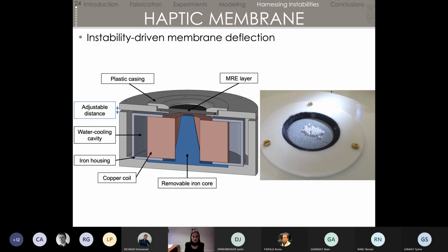So here you have at the top of the device an MRE layer inside a plastic casing, and then it's deposited on top of a coil with an iron core. And as you switch on and off the magnetic field, you can see that deflection of the MRE layer on the video on the right. And so the idea is that layer wants to fully turn, but because it's attached all around, it will deflect and create those jumps that you can see.